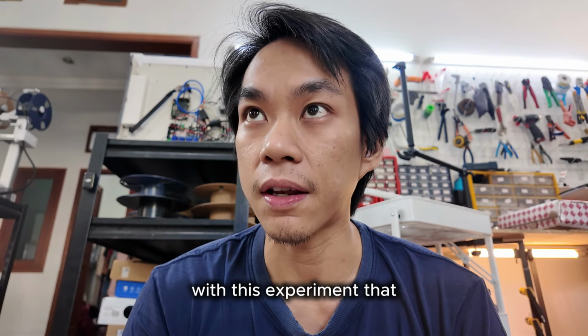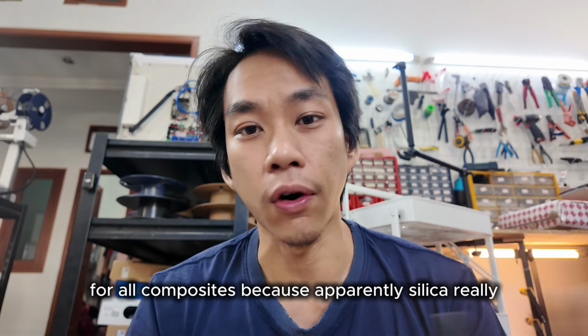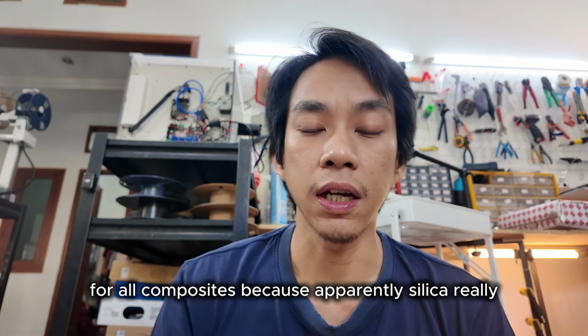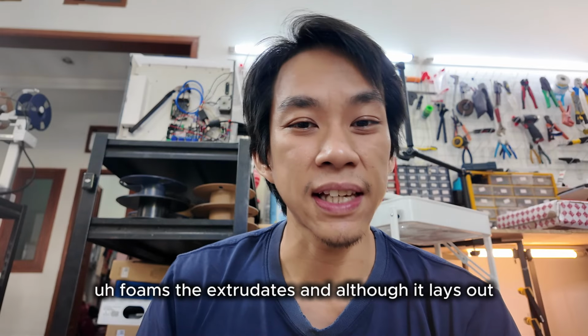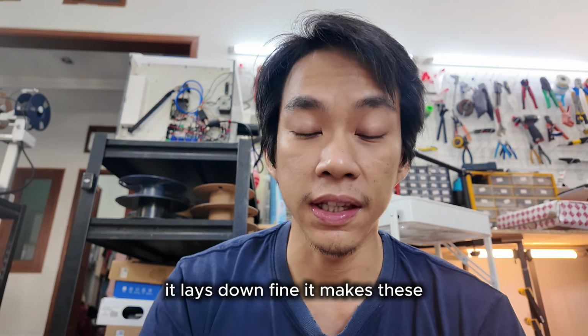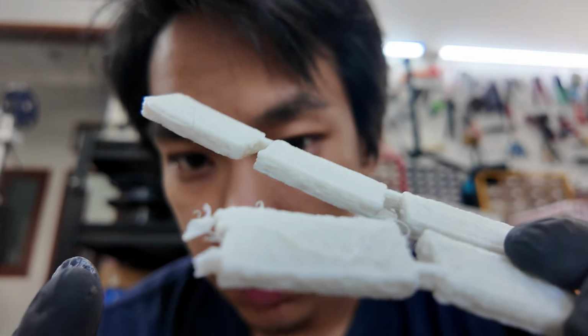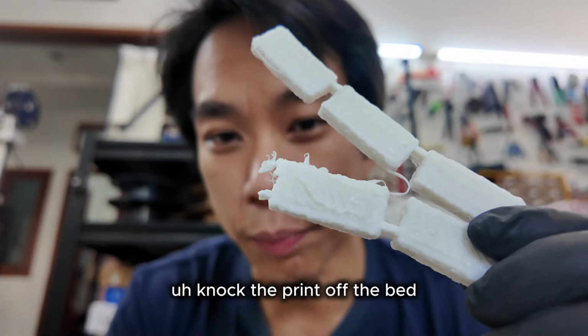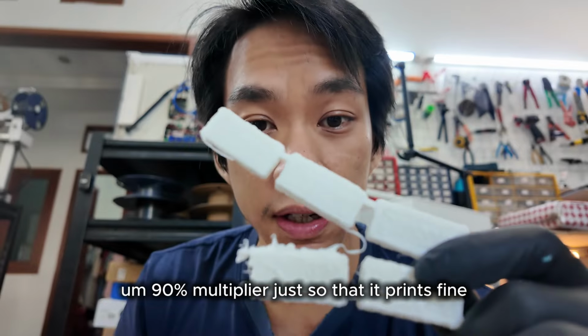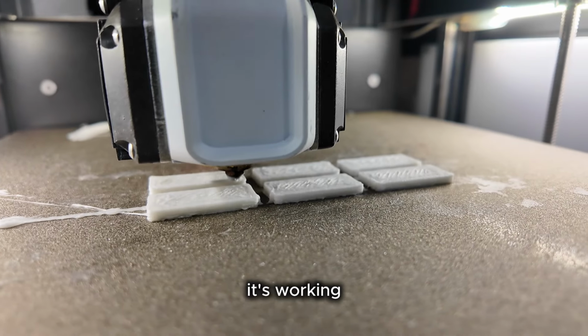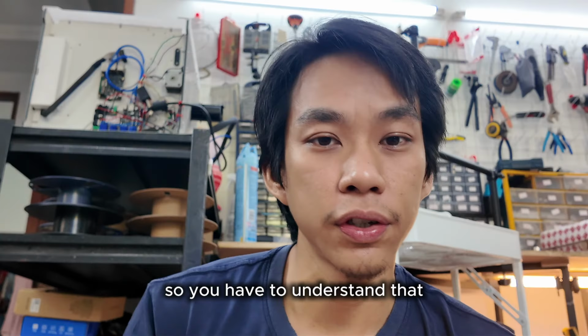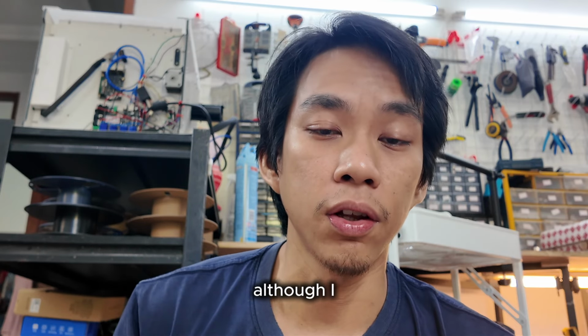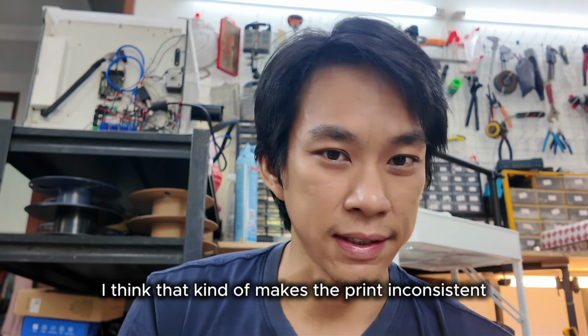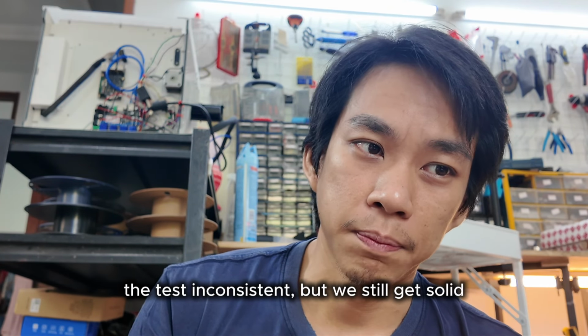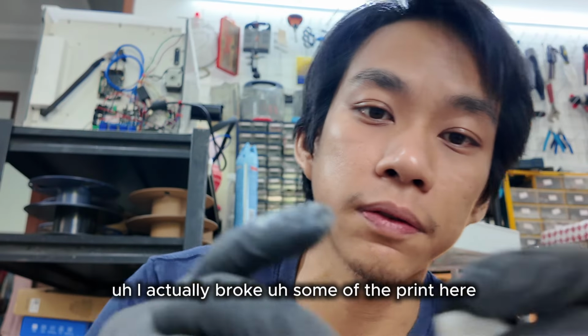So the thing with this experiment is that you have to understand we can't use the same flow rate for all composites, because apparently silica really foams the extrudates, and although it lays down fine, it makes these bumps. And these raised portions knock the print off the bed, so I've got to use like a 90% multiplier just so that it prints fine. It's working like the other specimens, so you have to adjust flow rates for each print. Although that makes the test inconsistent, we still get solid fills.